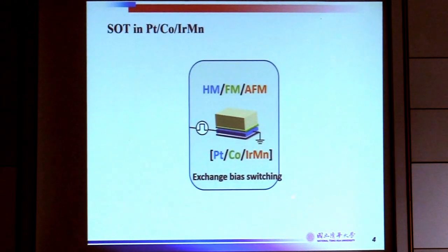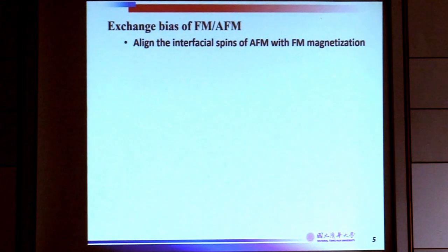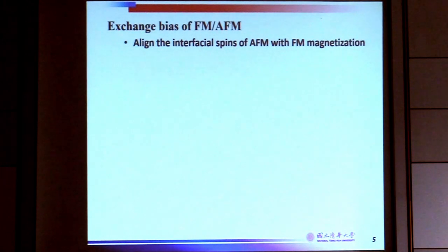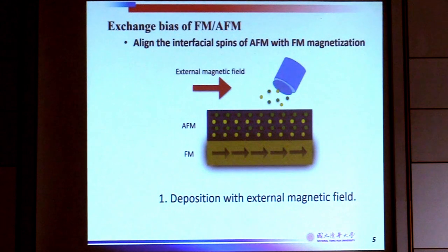We would like to introduce IrMn to replace one of the platinum layers. Let me give a brief review of exchange bias. We typically have two ways to build exchange bias. One way is to deposit the ferromagnetic and antiferromagnetic layers in the presence of a magnetic field — for example, by sputtering — where we apply an external magnetic field to align the magnetization of the ferromagnetic layers, so when we deposit the antiferromagnet on top, exchange bias is automatically built.